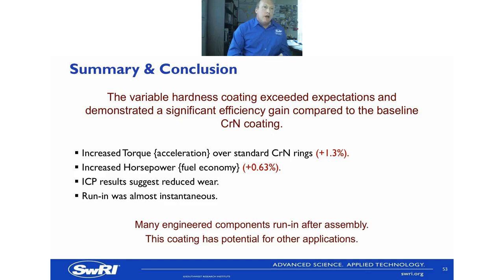So to summarize, the variable hardness coating actually exceeded expectations, demonstrated significant efficiency gain compared to the baseline chrome coating. We saw increased torque, which is equivalent to acceleration of about 1.3%, increased horsepower, which is fuel economy of about 0.63%. On top of that, the ICP results suggested reduced wear, which is highly advantageous, and run-in was almost instantaneous, which doesn't matter so much for everyday vehicles, but for race vehicles, competition vehicles, is very, very beneficial.